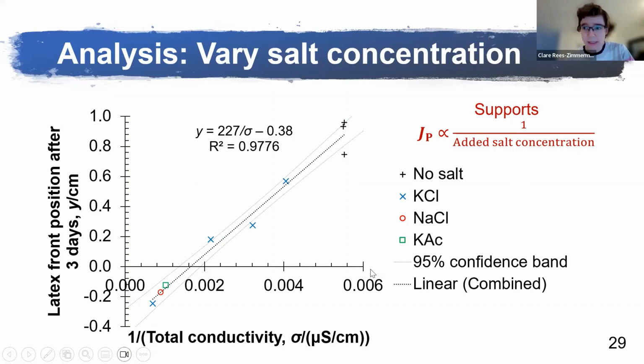So I repeated this experiment, varying the background salt concentration. I also did some different background salts. On this slide, I've plotted the latex peak position after 3 days against the reciprocal of the conductivity. And you see you get a nice straight line, which is supporting that the diffusiophoretic flux is inversely proportional to the background salt concentration. That's supportive. It is following the equations that I wrote down earlier.